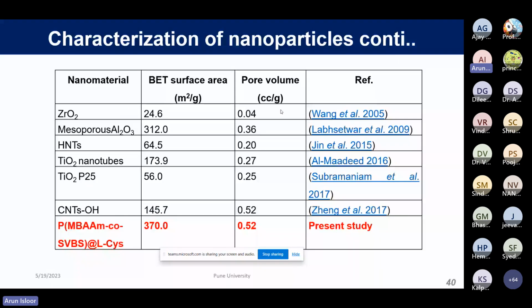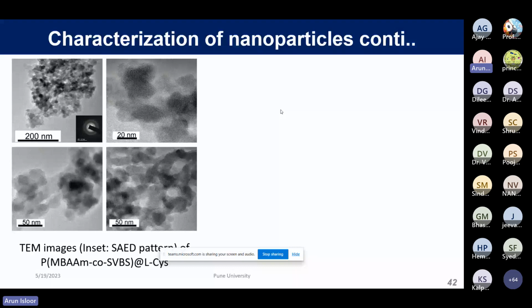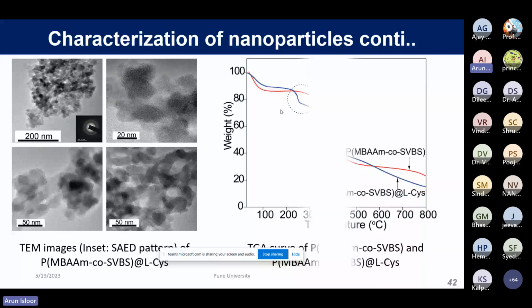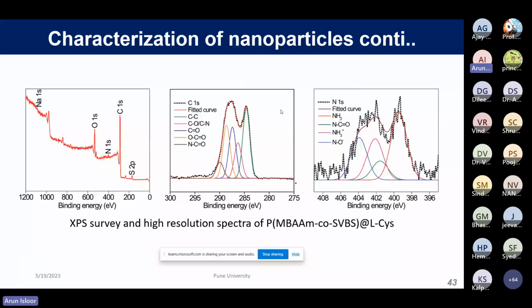Of course, the BET surface area was used for the characterization of this material, and the red colored one shows the more efficient one, and FTIR before and after. Similarly, the TEM images show some sort of agglomeration of those nanoparticles. More or less the particles were smaller than 50 nanometer size. Similarly, the XPS also confirmed the type of bonding present in these newly synthesized polymer nanoparticles.